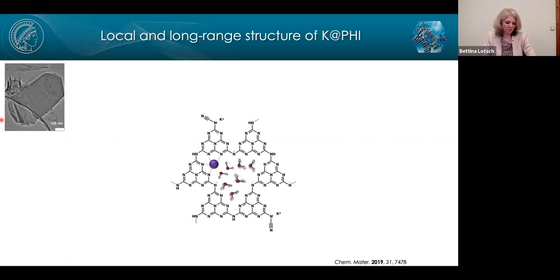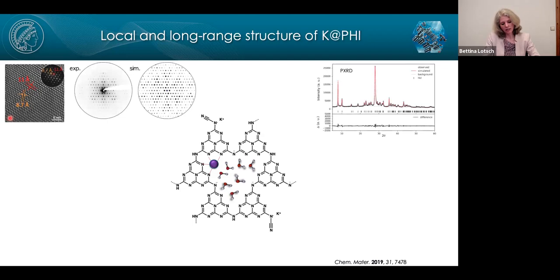So here's a TEM image. You see a layered morphology and particle sizes. This is actually a very nice sample. Particle sizes are around, let's say, lateral sheet extensions around 80 nanometers to a couple of hundred nanometers. Now, TEM electron diffraction tells us that this is a crystalline system, a nanocrystalline system. So we don't have single crystals, but we can clearly use the crystallinity for structure solution.